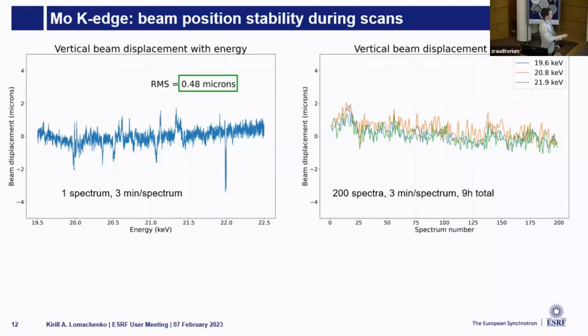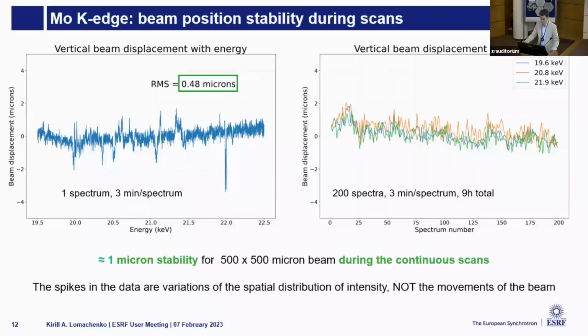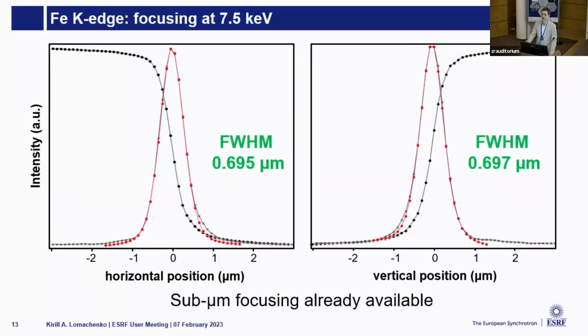And then this is over energy, and this is over time. We measured the spectrum for 9 hours, and we see that at given energies, the beam position does not change that much. So this positional drift is also on the order of 1 micron. And then we focus, because we'll do a lot of focused beam studies. So we will be operating quite a lot in focused mode. And these results were achieved basically by the end of last week. Using our KB mirrors, we were able to focus down to 700 nanometers in both directions. And that is the way we're going to operate this week for the first user experiment.